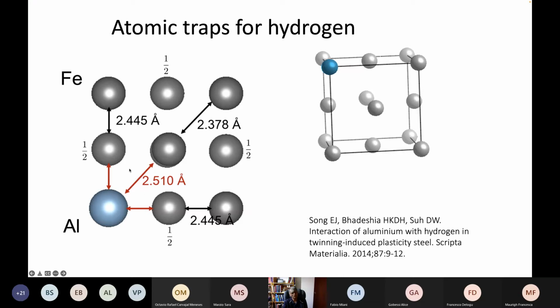So there's more space created in the interstices between the substitutional atoms. And that is where hydrogen gets trapped. So it's a deeper trap for hydrogen than inside the lattice, and therefore you prevent hydrogen embrittlement of TWIP steels. Now, although I said that